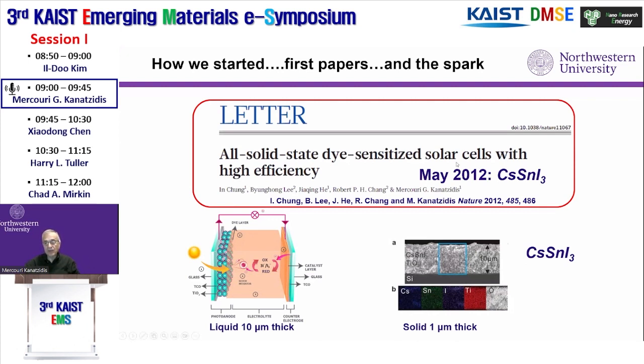Now, we were working on perovskites in 2008, 9, 10, for a different reason. And in 2012, I got together with my collaborator, Bob Chang at Northwestern, who was working on Gratzel cells. And he was trying to stabilize them and make them solid. And so I suggested to him, we use the perovskite as the replacement for the solvent because it could do the same job. It could actually transport the holes across the device. And I suggested that because I knew a lot about this material from all the work we did the 3 years before that.